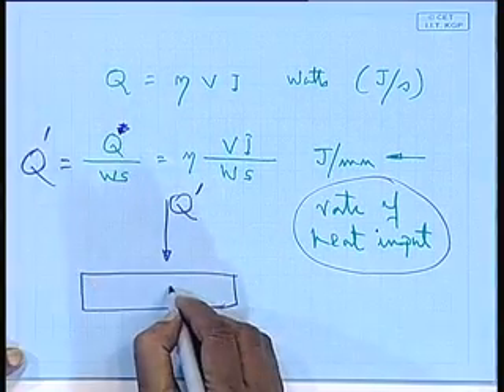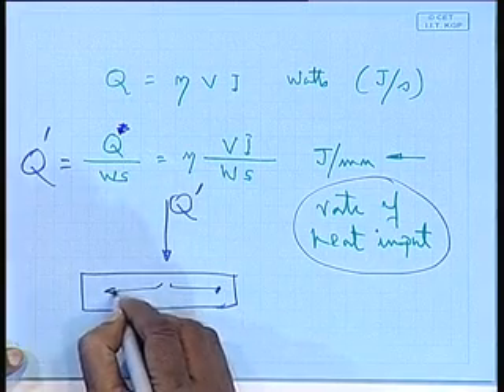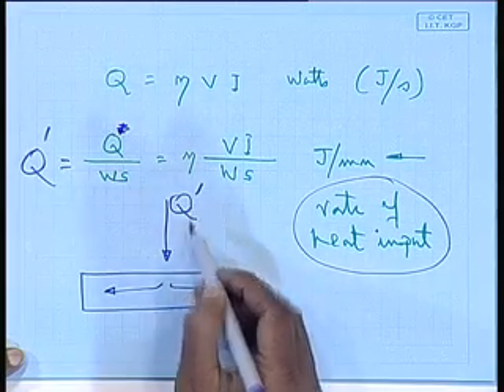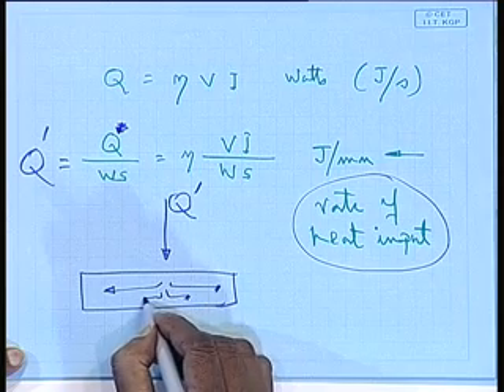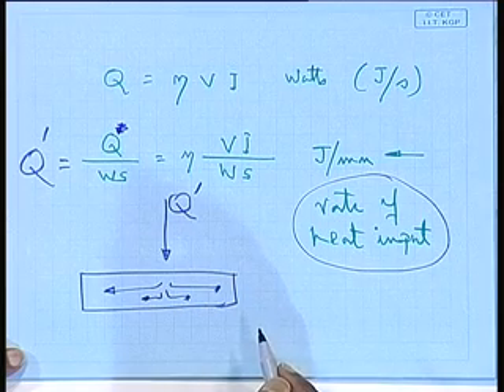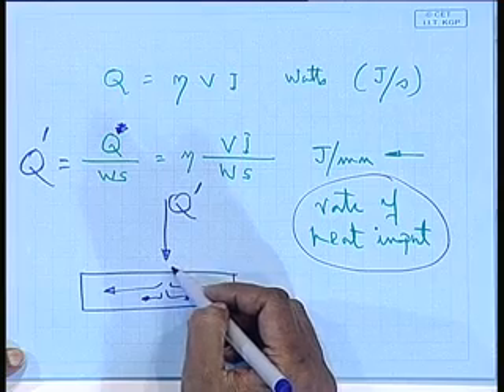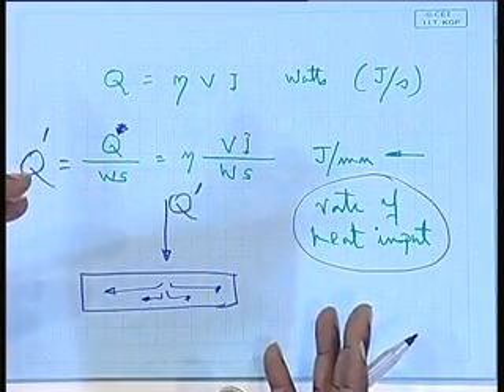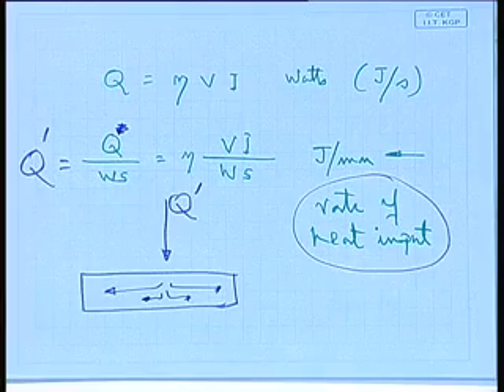If more is going in, means more heat conduction. If it is less, then it will be less. Simple. More joule per millimeter means it has to get dissipated, isn't it? That means more part of the plate will get heated up, and more part of the plate getting heated up means you have higher stresses, higher deformations, higher heat affected zone, higher melting zone. Starting from the fusion zone will be more, heat affected zone will be more, more heat is going in. So, more thermal stresses, more deformations.